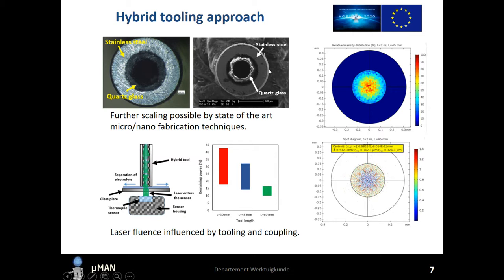Since the wall of the metallic electrode is not a perfect reflector, we get a combination of diffuse and specular reflection. So it's not a perfect waveguide, and leaky modes propagate inside the tool. Here is a schematic of how we determine the efficiency of our hybrid tool, that is, how much power output we are getting in relation to the power applied into a controller. If we have a new tool on the first day, we can get as high as above 40% of the power applied to the controller.